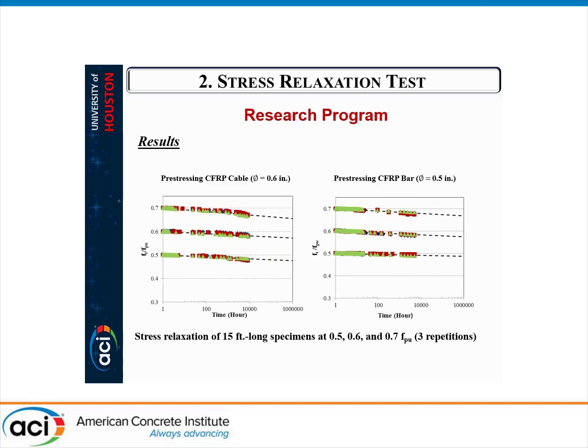Now I would like to talk about some of the results. Here I have the stress ratios with respect to the logarithm of the time for all the specimens at the same length, but with 3 different initial prestressing levels. As you see, for both CFRP cable and bars, we observe the linearity between relaxation and log time, and also higher stress level resulted in higher relaxation as we expected.